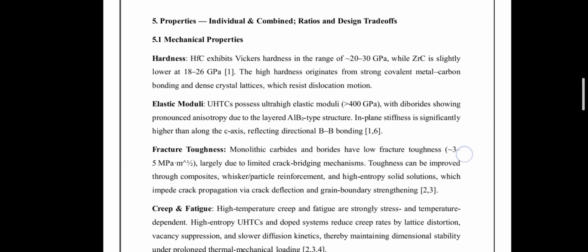Now we will move towards the properties. First are the mechanical properties, hardness and the elastic response. Ultra high temperature ceramics exhibit exceptionally high hardness and stiffness due to the strong covalent metal non-metal bonding and the dense crystal lattice. For example, hafnium carbide shows hardness in the range of 20 to 30 GPa, while zirconium carbide is slightly lower, 18 to 26 GPa.